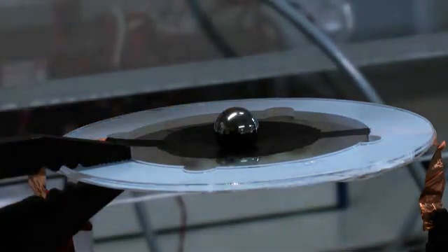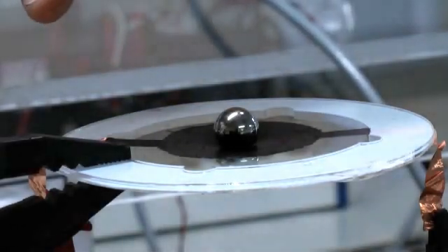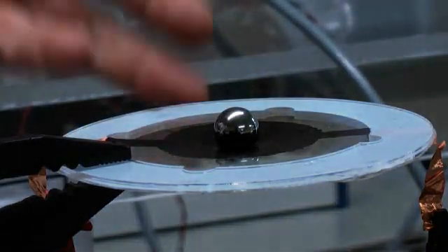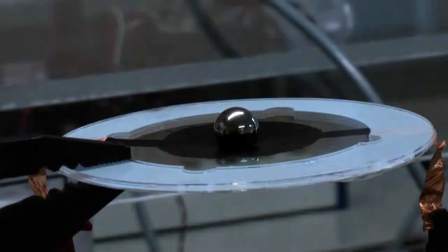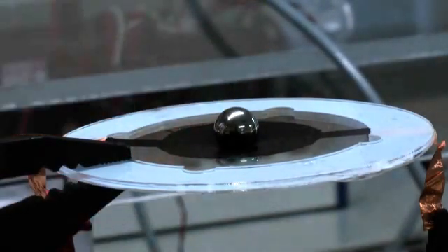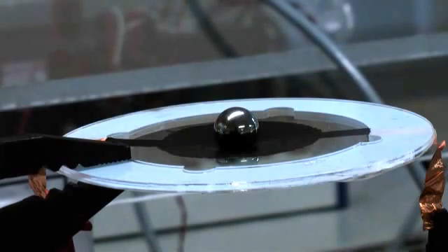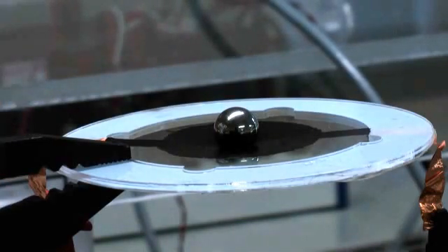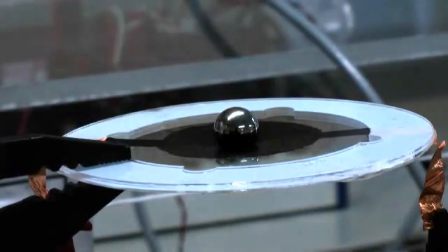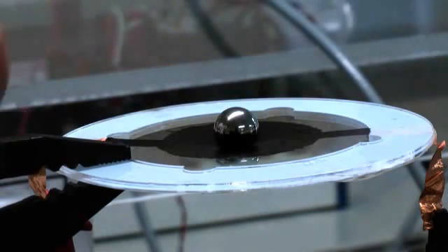The reason it moves up and down is because we have these electrodes on the top and on the bottom of the material. When we apply electricity, these electrodes expand. When they expand, the material becomes slack, it becomes loose, and the ball is free under gravity to move up and down. This experiment shows two things: the membrane can deform in response to electrical stimulation, and we can turn the areal expansion of this membrane into something useful, which is moving a ball up and down.